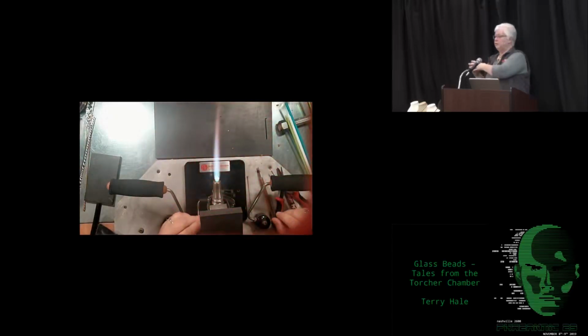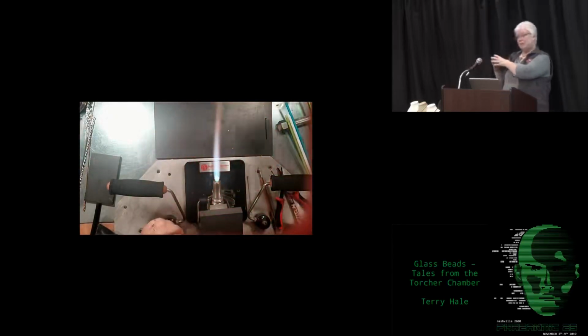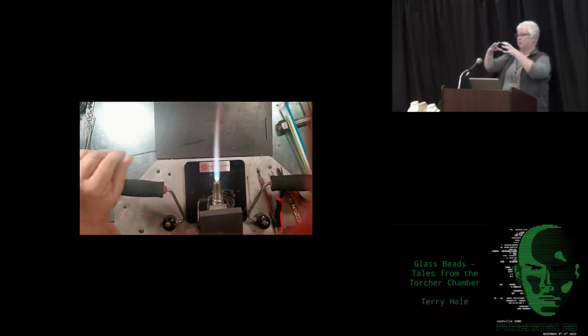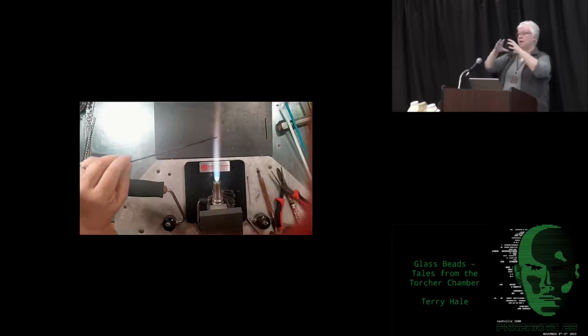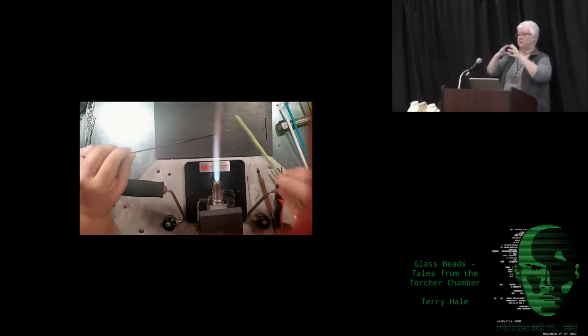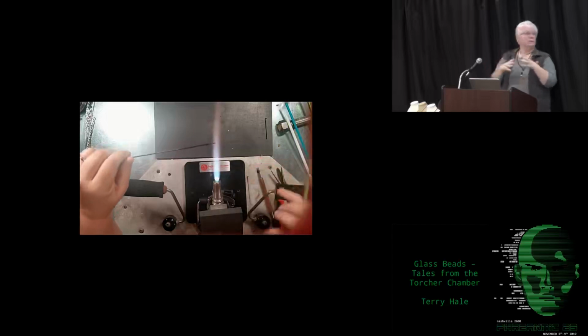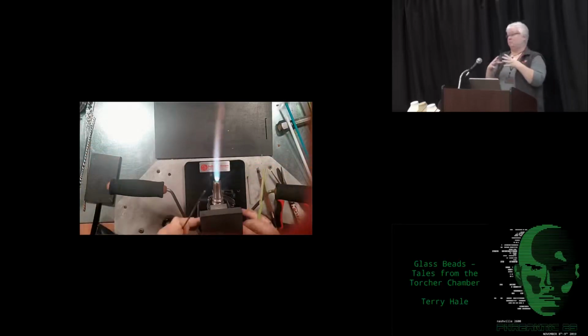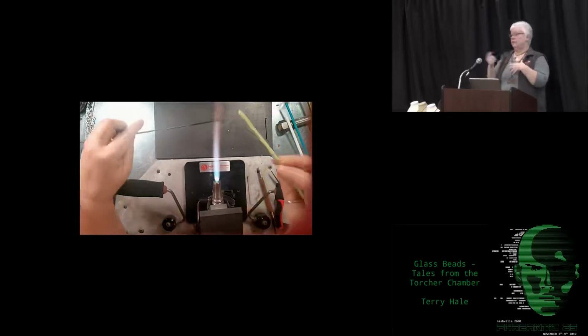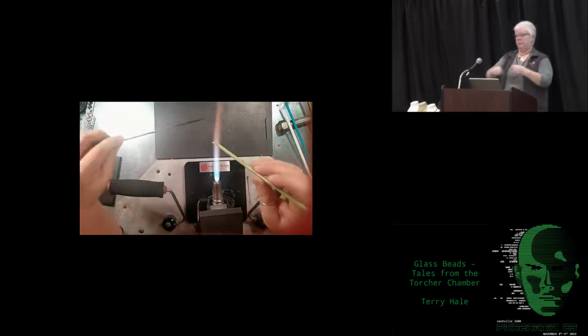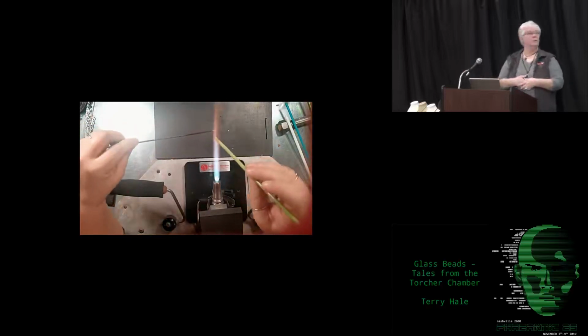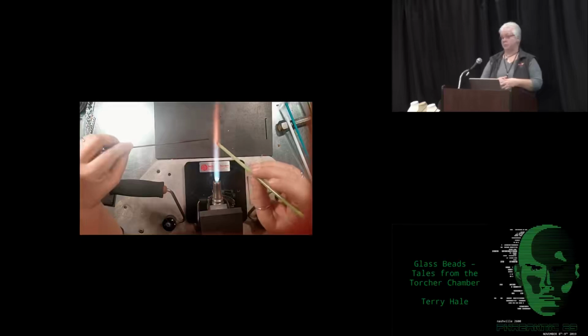It sits at 960 degrees for an hour, which is just below the melting point. And it lets that bead get exactly the same temperature all the way through. And then my kiln steps down. It cools off over several hours so that it's a very slow cooling process. Your craft store beads, they don't do that. They're just stuck in sand, if anything, or they make them on the rod and throw them in a pile. So basically an annealing process. It's an annealer, yes.